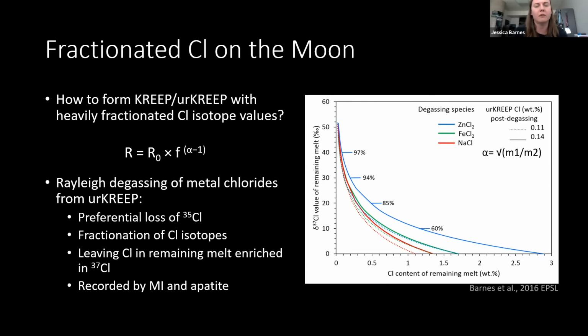And so we undertook some Rayleigh distillation modeling to see if we could compute this and try and trace the chlorine isotope fractionation. If you're not familiar with the Rayleigh equation, R is the chlorine isotope composition remaining in a melt. R0 is the initial chlorine isotope composition before any crystallization, before any loss has occurred. F is the fraction, and this alpha factor is the relationship, the square root of the masses of one of the isotopologues to the other.